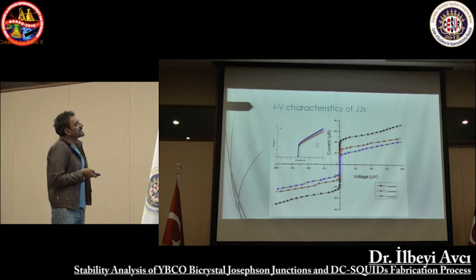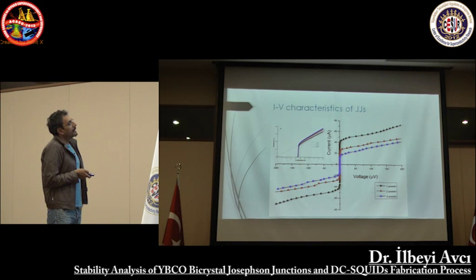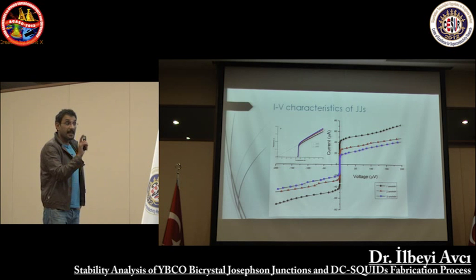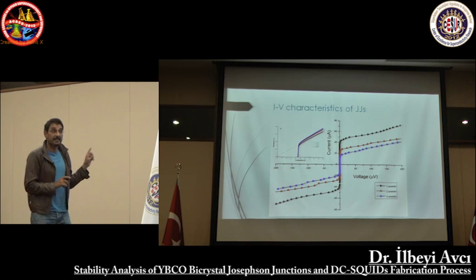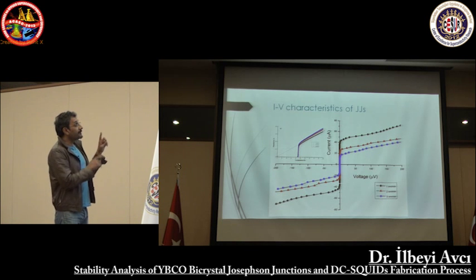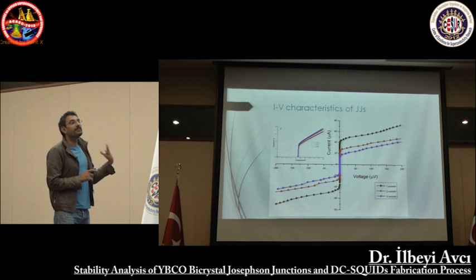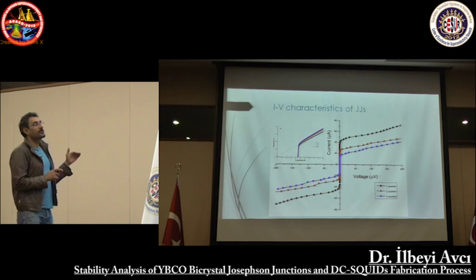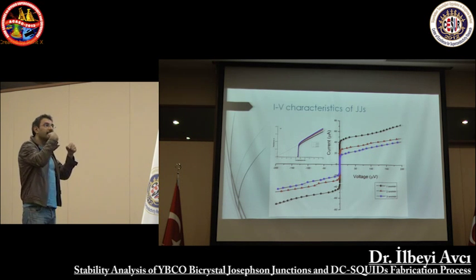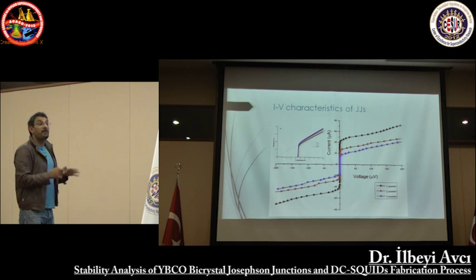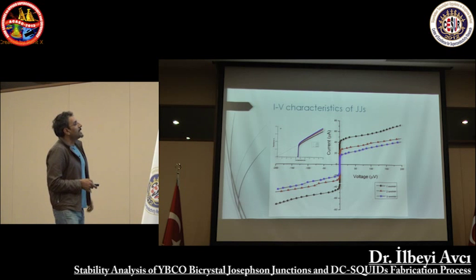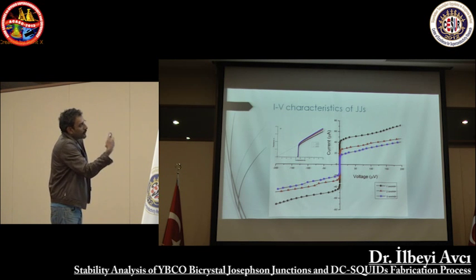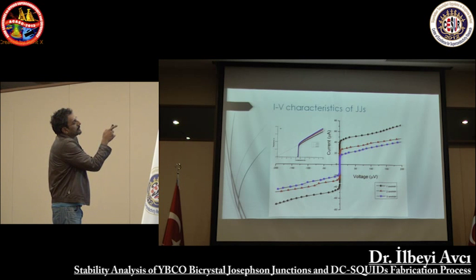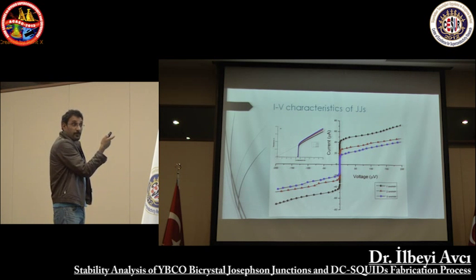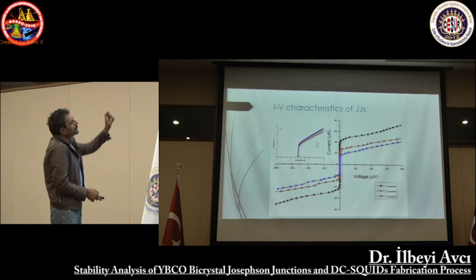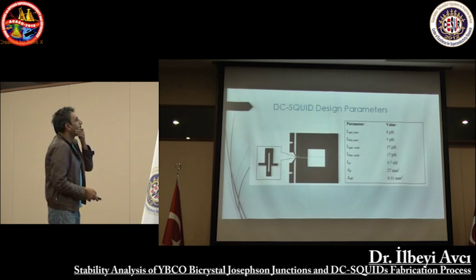These are the parameters. We have discussed the deposition rate of the YBCO thin films. Of course, these junctions are bicrystal Josephson junctions, so the deposition rate of the thin films is very important, because the film formation just along the bicrystal line is very dependent on the thin film growth rate. As you can see, as the growth rate increases, the critical value of the Josephson junctions decreases. So we optimized this value at 1 nanometer per minute.